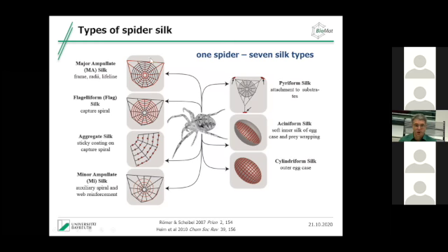They start with the frame, which is the so-called major ampullate silk. Then this is accompanied by the capture spiral. This type is called flagelliform silk. This is just a mechanical setup. In order to keep the prey in the web, it needs some glue, and this type of spider uses a liquid glue. There are also other spiders that have a dry adhesive, wool-like structure, but these spiders here use a liquid glue, which is called aggregate silk.